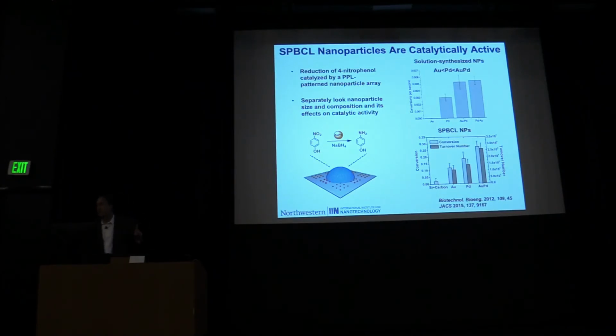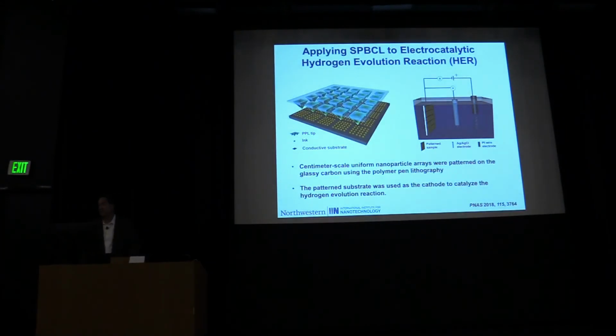That's true. So the first thing we did is we said, let's go find a catalyst that we already know is a working catalyst. If we get confidence there, then we can go and more confidently look for unknowns. So in this particular experiment, we're looking at this particular hydrogenation reaction. It's known that gold and palladium particles made via solution methods are better than pure gold and palladium particles alone. Well, we can synthesize those, I think I convinced you of that, and then we can study that process. If you're looking at both conversion or turnover number, you can see very clearly that the gold and palladium outdoes the monometallic systems, confirming what the literature has suggested. So now we can begin to think about discovering unknowns.